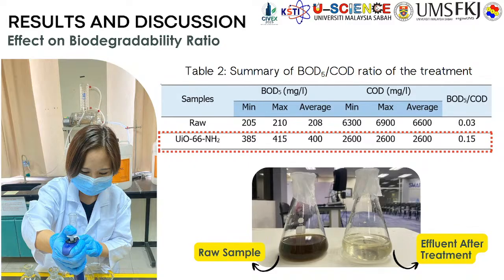Lastly, this table shows the biodegradability ratio before and after treatment. As we can see, the raw BOD5 over COD is 0.03 and it has enhanced to 0.15 after the treatment. So this is the raw sample before, and using the optimum condition of dosage 0.17 and pH 5, this one is the sample after treatment.